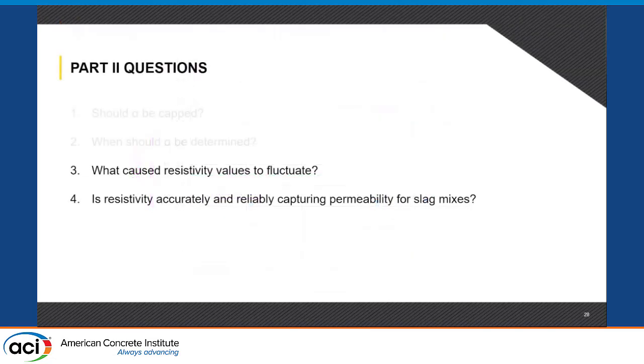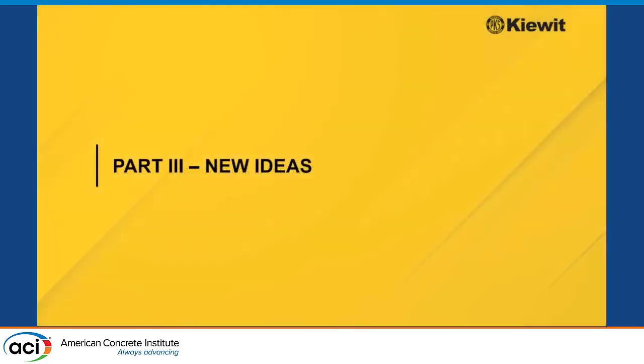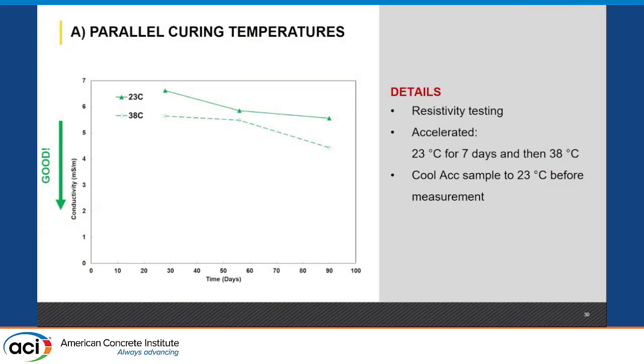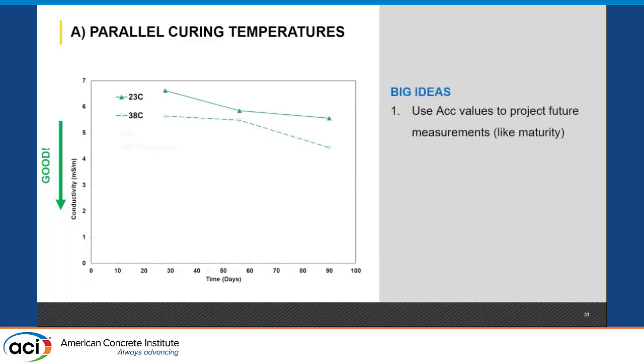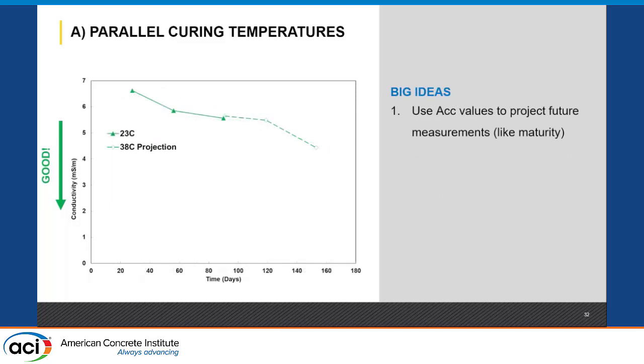So questions are, what caused resistivity to fluctuate, and is resistivity accurately measuring permeability for these slag mixes? With this in mind, we had to do something new, so we had some new ideas. The first one is, what if we do a bunch of different measurements at different temperatures, if we accelerate it? So we put resistivity samples at 23 for 7 days, and then at 38C, and we found that we were basically trying to predict the future.